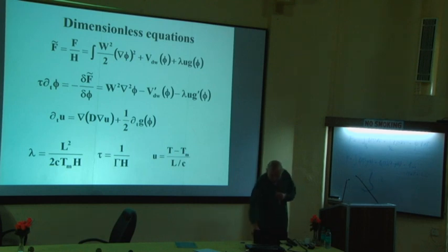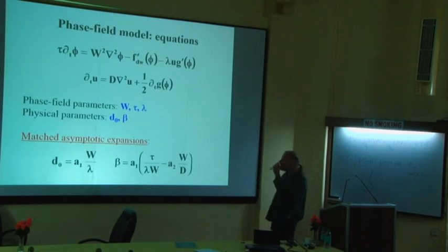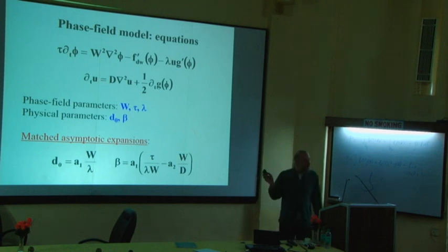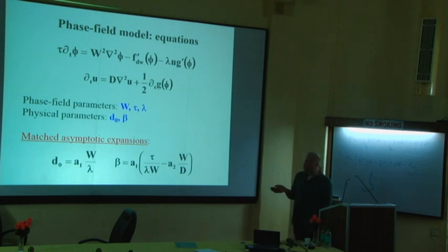Okay, so the result is we have written down a phase field model which amounts to these two very simple coupled equations. Okay? Sort of Allen-Cahn equation. The only new thing is that this is coupled now to another dynamic field U. In the magnetic model, U would be the magnetic field, so that would be a constant. Here now, U is a spatially varying function because it's the temperature. And this spatially varying function obeys another dynamic equation.